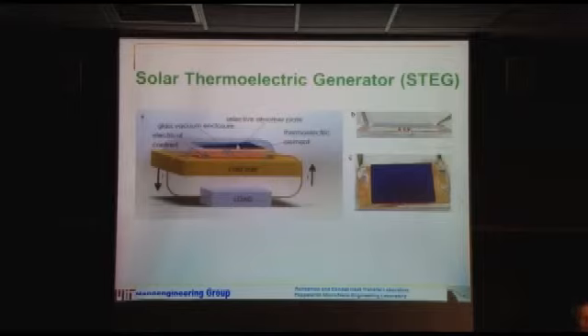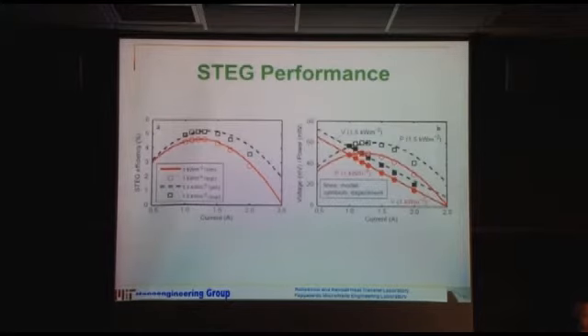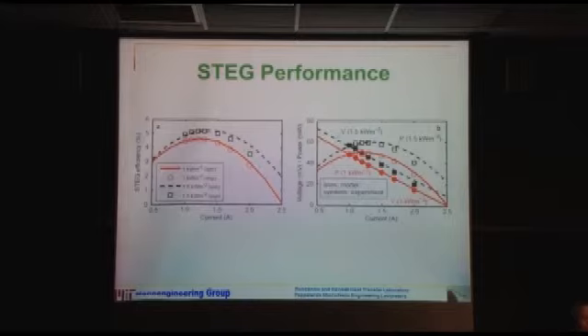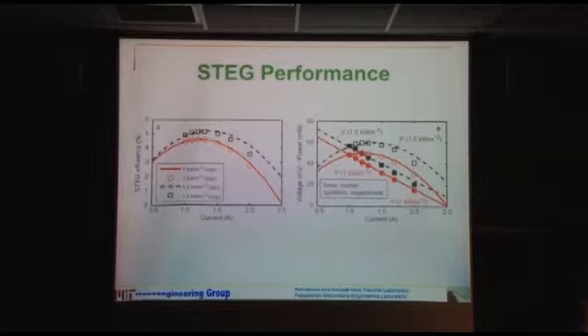And see the beauty of this is the solar energy absorbed by this absorber. They are flat, but the heat has to be concentrated through this absorber into the leg and create a temperature difference. So this is the efficiency we measured. And here there is no optical concentration at all. This is a 1.5 optical concentration, and that's about 5%. So you immediately bring, because I said in the 1950s this efficiency was about 0.6%. So that's a real large step for this technology.